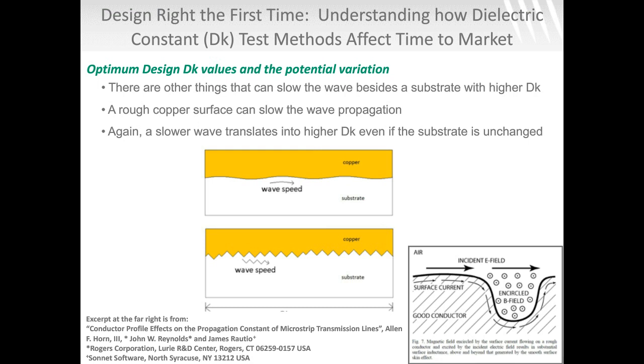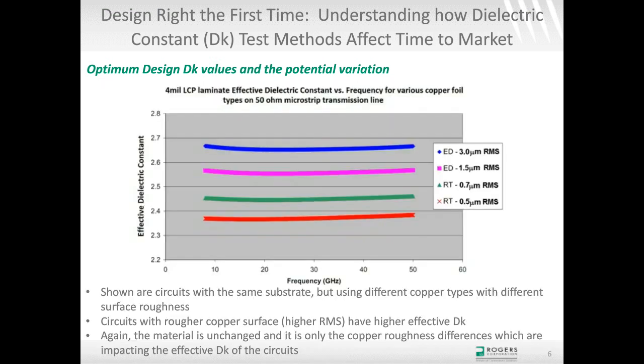A good way to illustrate that is a chart that's shown here. We did the study several years ago, and the substrate is 4 mil LCP, the same lot of LCP. Everything's the same for the dielectric, so we tried to keep the dielectric the same as much as possible, but we used four different types of copper. We measured the copper surface roughness with a non-contact laser profilometer before we made these laminates, and we made four different laminates with the exact same substrate with different copper roughness, knowing what the roughness was. We sent off these laminates, had circuits made, came back, and we did our microstrip differential phase length method, and I'll explain that test method a little bit later.